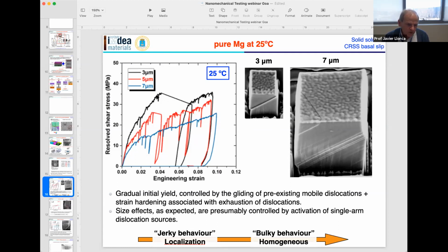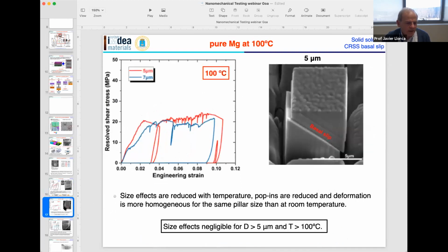And of course, as you increase the size of the pillars, you have more homogeneous deformation, and then the amount of size effect that you have is decreasing. So what you can see here is that you have to be very careful, because if you have very small micropillars, you cannot say that this is the critical resolved shear stress for basal slip, because what you have here is size effect, and this value for the onset of the formation of a slip band is controlled by the small dimensions of the micropillar, and is also controlled because of the limited number of dislocations in the initial micropillar.